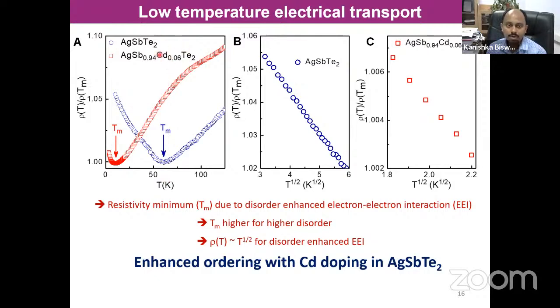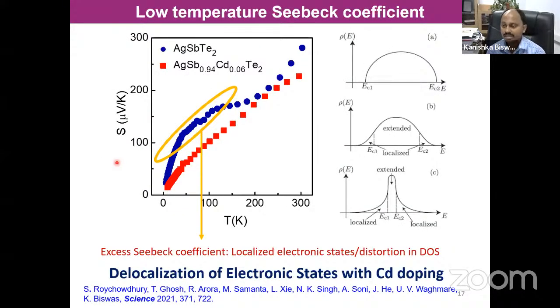As soon as I dope 6 mole percent, we see the minima is at 11 or 12 Kelvin. So cadmium actually orders the silver and antimony partially and shifts the minima to low temperature, and you see a delocalization of the electron states. Now let's see what happens if we measure the low temperature Seebeck coefficient.